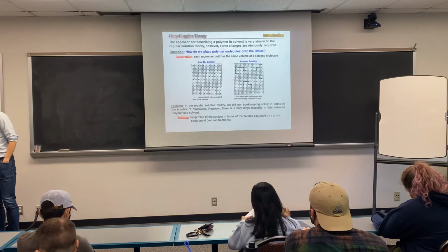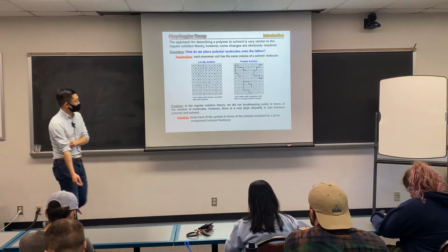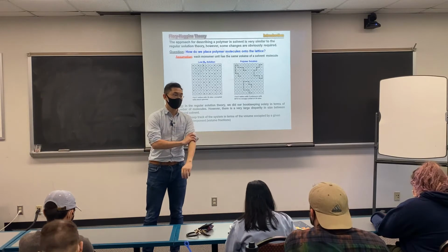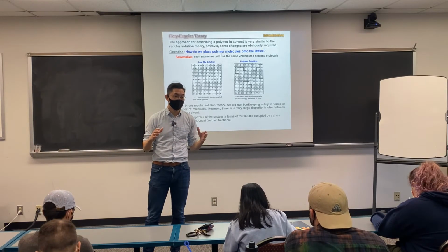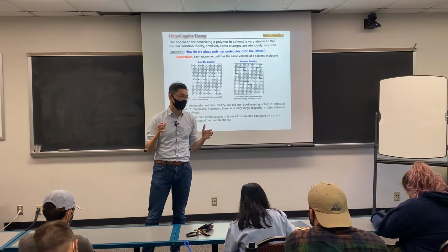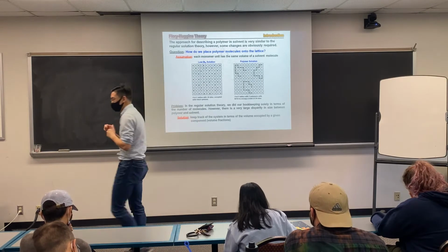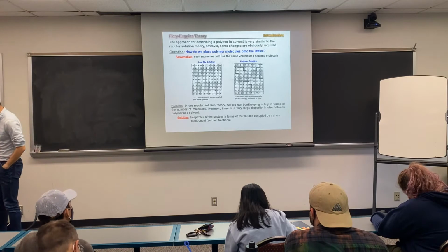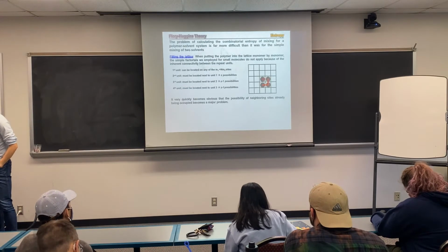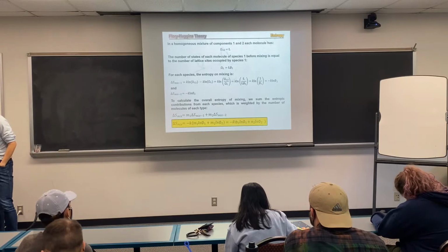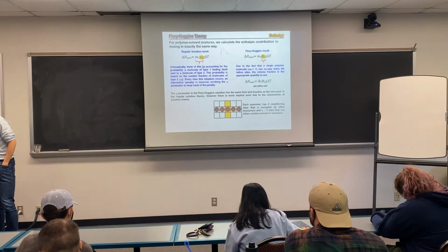But as you can see, entropy always favors mixing, but in the case of polymer solvents, your entropy is less strong in pushing the system to the mixed state. So when your chi is high enough, it will phase separate. And this is a typical outcome in many high molecular weight systems with unfavorable interaction. So we have covered this part.